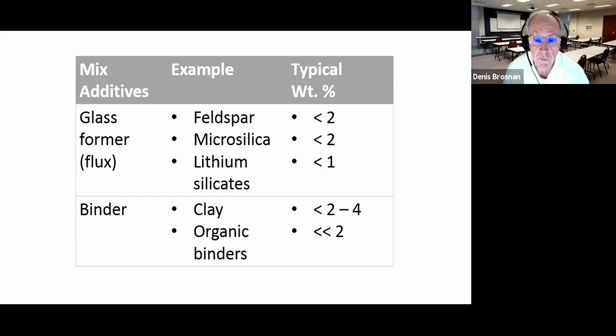Well, that's some of our raw materials, but not all, because typically we will have to add binders to these products. They're made by various pressing processes, either dry pressing or isostatic pressing, whatever the case may be. But typically in the products that contain a little less than 96% alumina, we might use clay as a binder in pressing. If we're up at 99% alumina, we probably will use organic binders, and these could be carboxymethyl cellulose or things of this nature, polyvinyl alcohol, whatever might be used in binding.